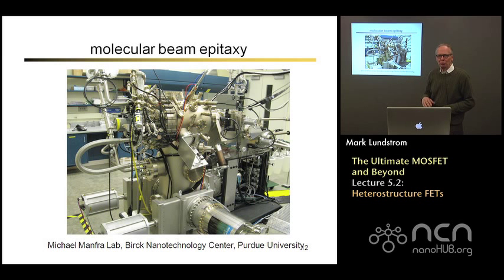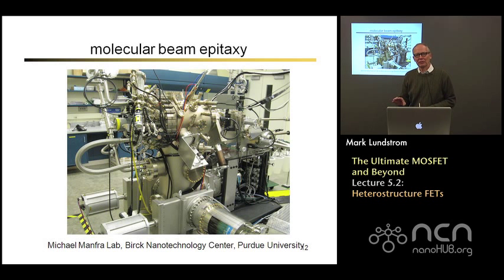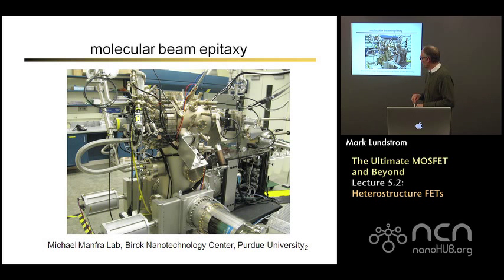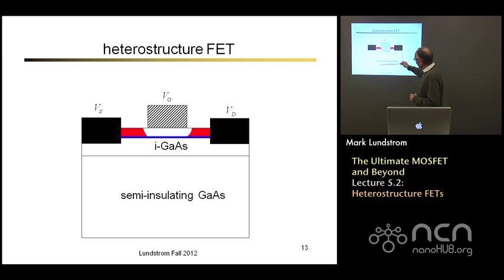These films are grown by epitaxy under very expensive and carefully controlled conditions. Here is Mike Manfra's lab at Purdue University. You can see the various sources that thermally evaporate arsenic, gallium, and other elements. This is a high vacuum chamber where the background pressure is very low, so you can evaporate atoms, give them plenty of time on the surface to find where they need to bind into the crystal. You can grow extremely high quality films leading to mobilities in excess of 1 million. So how do we make a transistor out of these films?